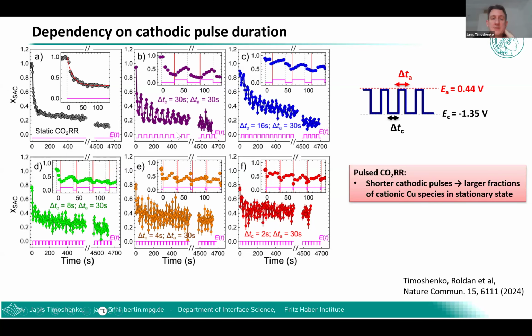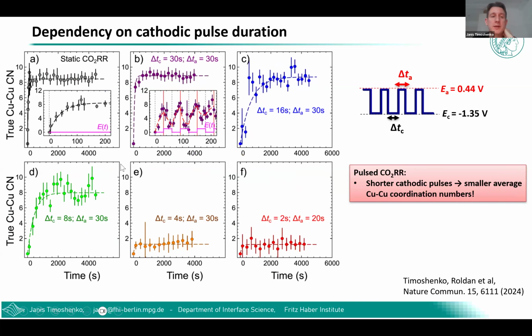Furthermore, if we analyze the particle sizes, we can see that this average copper coordination number also changes nicely from this original value of about 8 point something, which we saw for the static conditions and also for longer potential pulses, but we can reduce it to a coordination number of about 1 or 2 when we go to shorter and shorter potential pulses. So this means in this F condition, we really have very, very tiny atomic clusters, because a coordination number of 1 means that each copper has on average just one other copper atom in the vicinity. So it's basically copper dimers which we have in this catalytic material.